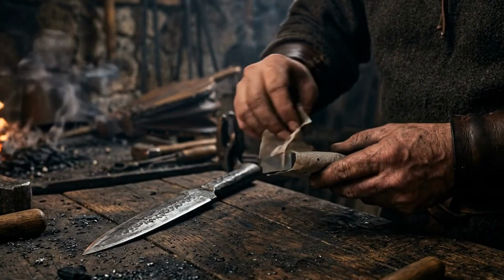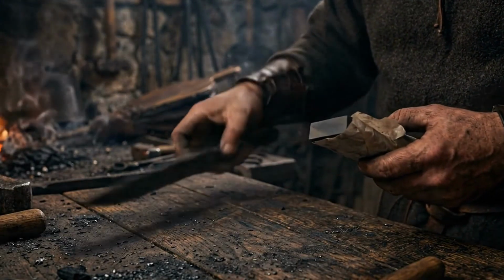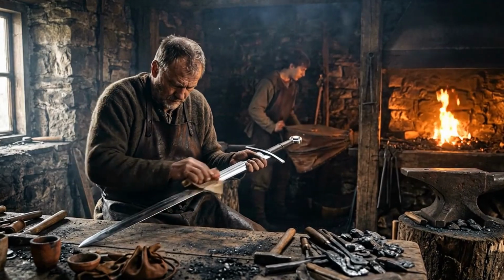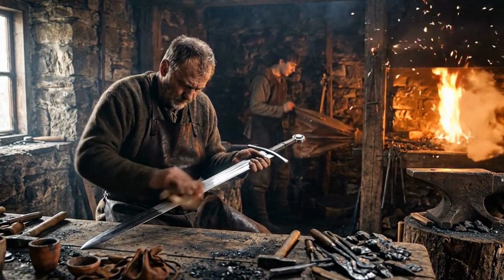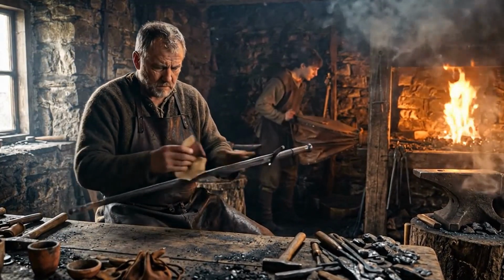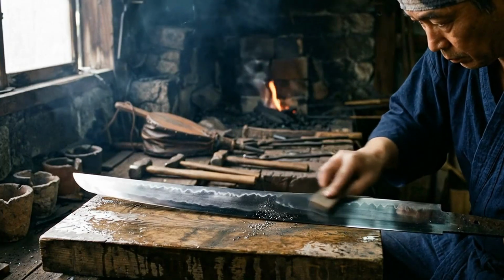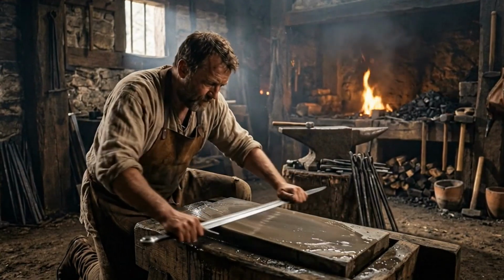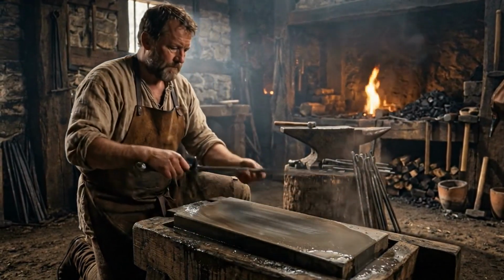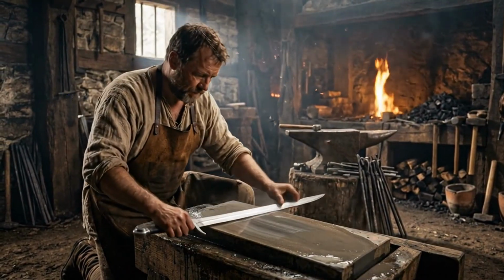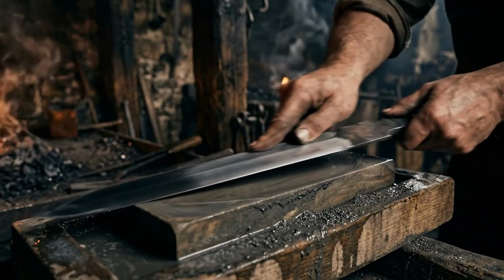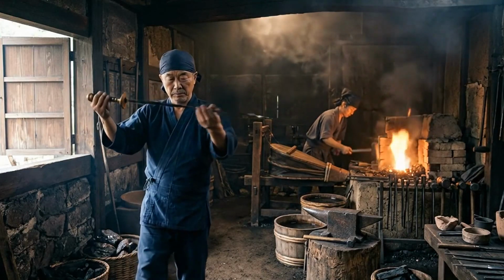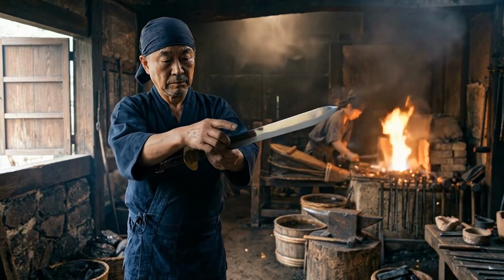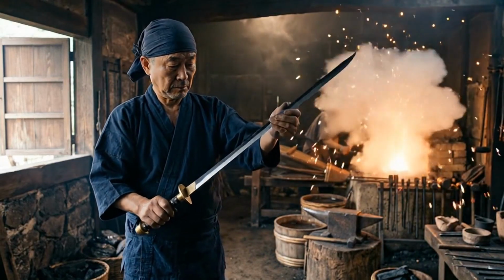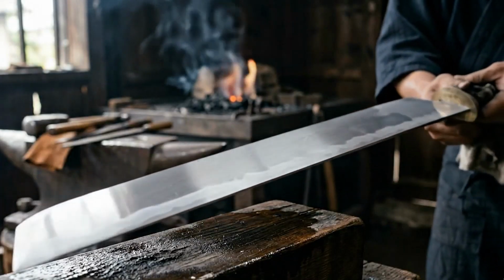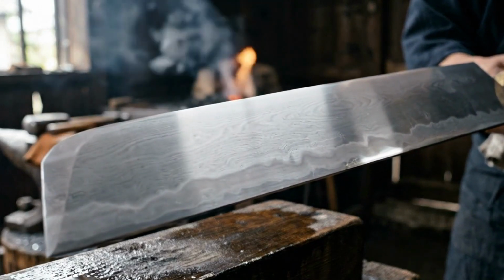The finest stones, some so delicate that they were used wrapped in paper rather than held directly, brought the blade to a mirror polish on the flat faces while leaving the beveled area near the edge in a slightly contrasting finish that made the hamon visible. The togishi worked by hand, moving the blade across stationary stones with controlled pressure and precise angles, spending days or weeks on a single blade. The final polish revealed everything: the hamon, the surface grain pattern called the jihada produced by the folding process, and any flaws in the steel that the smith's work had failed to eliminate.